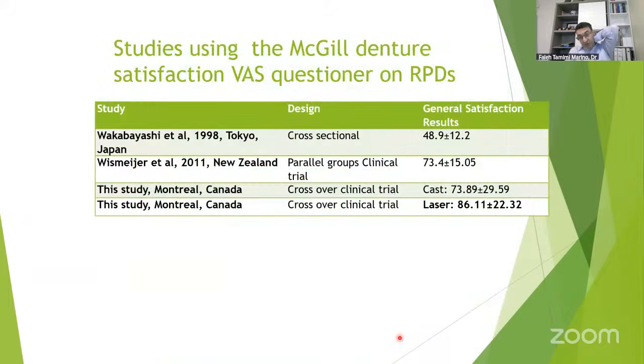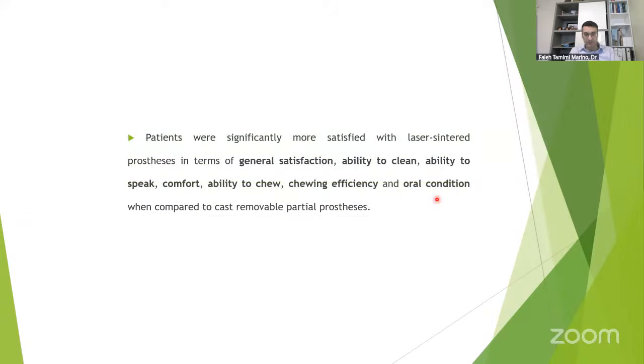If you want to put in context the satisfaction of patients in our study, most studies in the literature report satisfaction of patients with partial dentures between around 50% to 70% maximum. In our study, the cast dentures' patient satisfaction rate was around 70%, which is similar to the rest of the literature. But with laser sinter dentures, it was around 86%. So they were much more satisfied with laser sinter dentures than with cast dentures. So patients are very happy with these dentures.